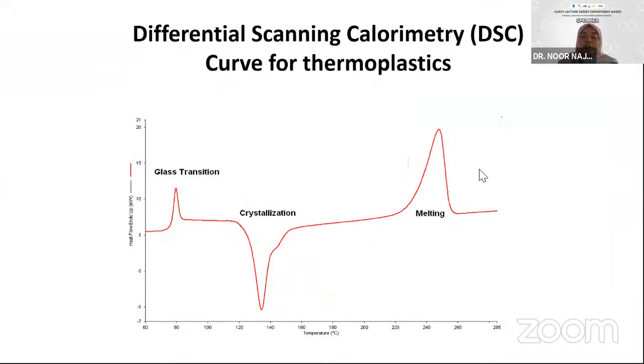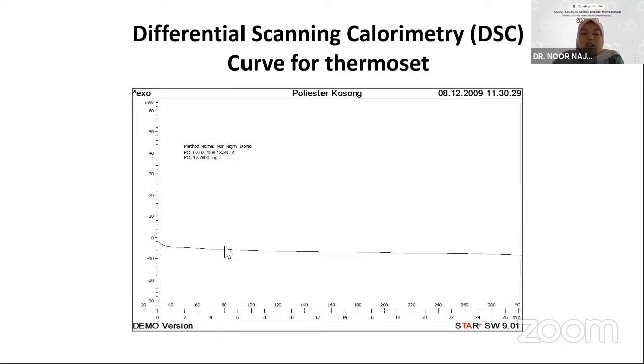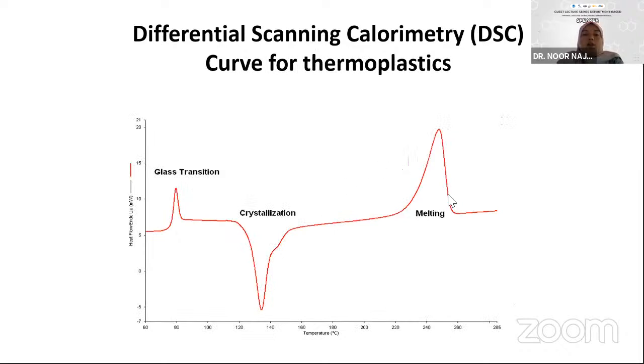Okay, so this is how to differentiate between thermoplastic and thermoset. If you have this kind of curve, which represents glass transition, crystallization and melting, or glass transition and melting temperature, this is for thermoplastic polymer. So that is one indicator to differentiate whether your sample is thermoplastic or thermoset. And if you have a thermoset sample and you send it for DSC analysis and it is fully cured, you will get this kind of graph, which is a baseline graph. Okay, so that is how you differentiate two types of polymer using differential scanning calorimetry: the baseline for cross-linked thermoset and this kind of curve for thermoplastic.